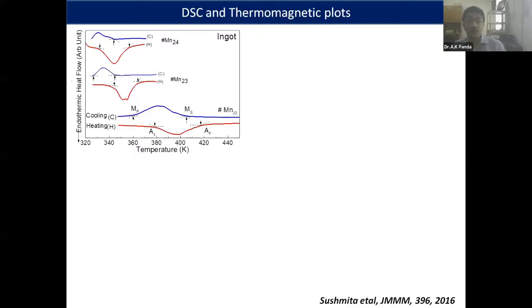Well, now I go to the differential scanning calorimetry just to show you some representations. What is happening when you go for increasing the manganese? You see that the red one is the heating cycle and the blue one is the cooling cycle. So what happens is when you increase the manganese content, the entire peak gets shifted to the left.